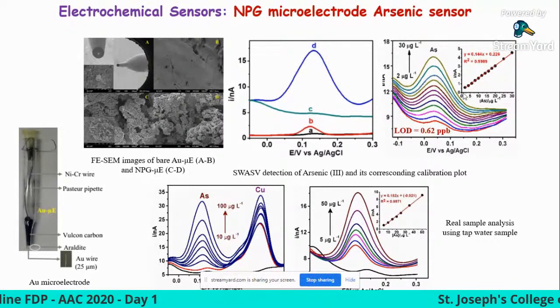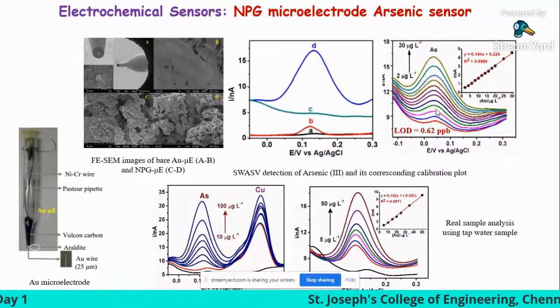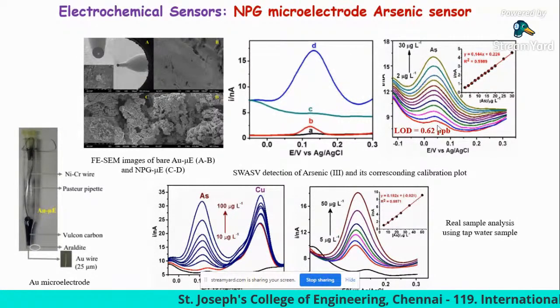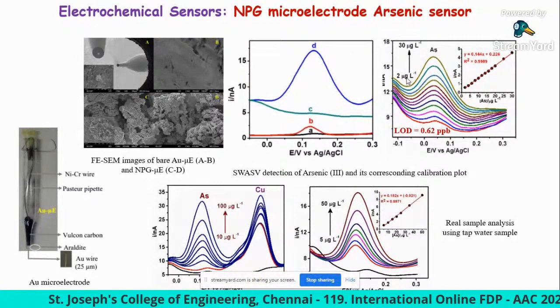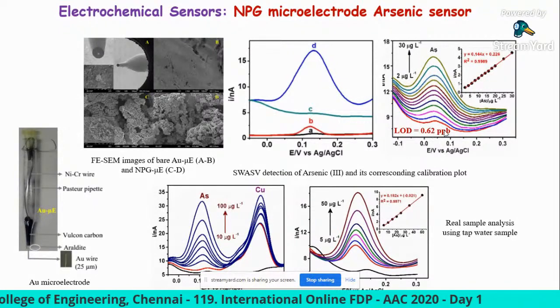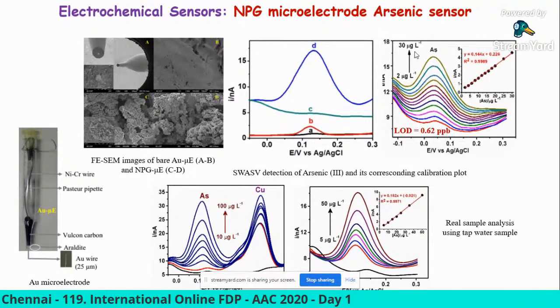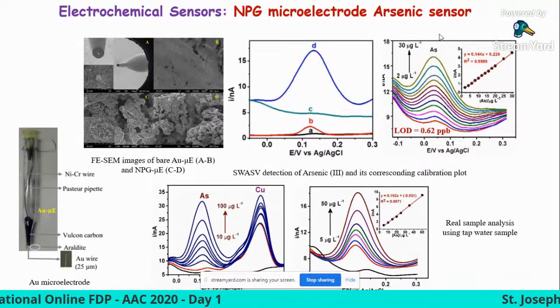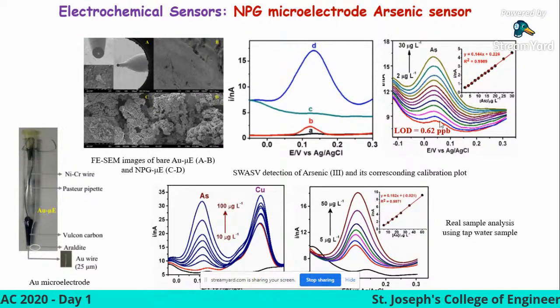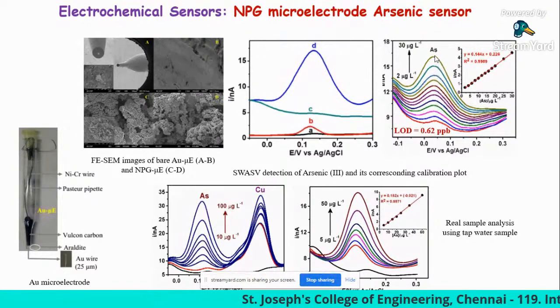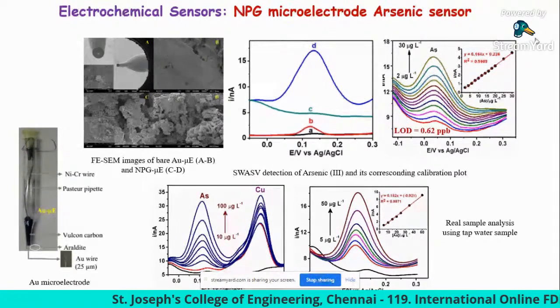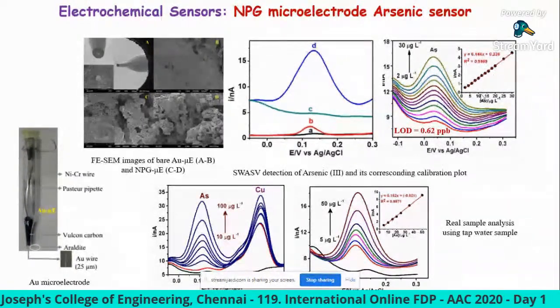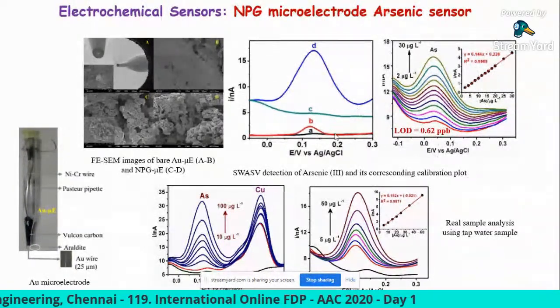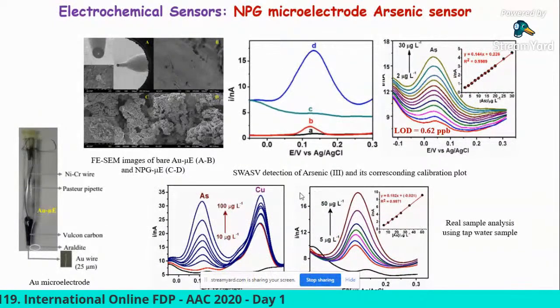This is the square wave anodic stripping voltammogram recorded for the arsenic sensor, starting from 2 parts per billion, ppb meaning parts per billion, to 30 parts per billion. The current response clearly increases with respect to the concentration. From this slope, we can calculate the limit of detection and other analytical parameters, of course.